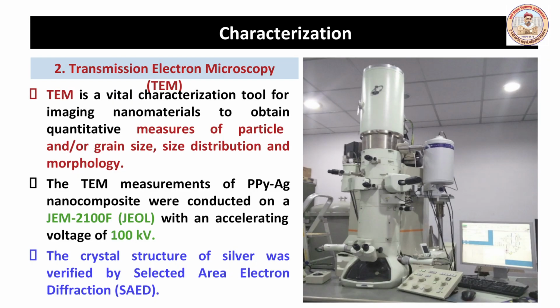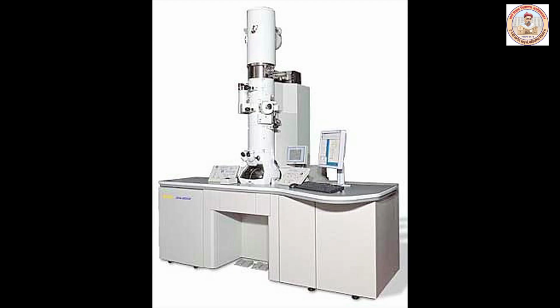The second characterization is transmission electron microscopy, that is TEM. TEM is a vital characterization tool for imaging nanoparticles to obtain quantitative measurements of particle and grain size, size distribution and morphology. The TEM measurements of PPY-Ag nanocomposites were conducted on JEM 2100F with an accelerating voltage of 100 kV. The crystal structure of silver was verified by selected area electron diffraction, in short SAED.